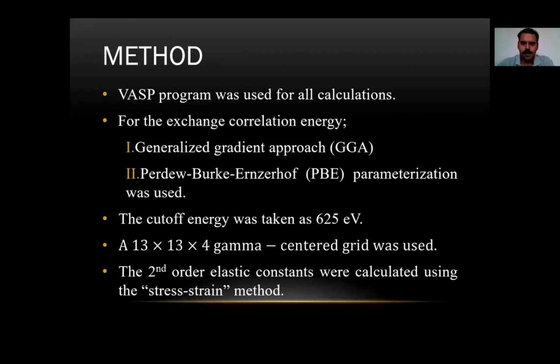Let's talk about the method we use. VASP program was used for all calculations. For the exchange correlation energy, generalized gradient approach, PBE parameterization was used. The cutoff energy was taken as 625 electron volts. A 13 13 4 gamma centered grid was used. The second order elastic constants were calculated using the stress-strain method.